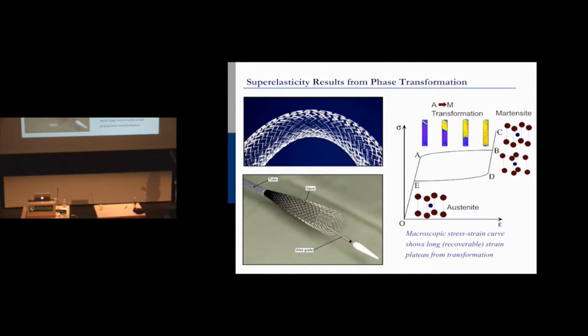What's happening when you do that is that the material is going through a phase transformation. So the material starts out, this is some data from one of our experiments. And I'll explain how we get this. The material down here starts out in a B2 cubic. We call it austenite. I'm using these words a lot. And you basically load the austenite pretty elastically. And then at some point right here, this is actually, from our data, a thin strip, maybe an inch-long strip of nickel titanium that we just pulled. What's going to happen is the purple, this is strain. The purple is really low strain, 0%, 0.5%, somewhere along there. The yellow is high strain, that's about 6%.